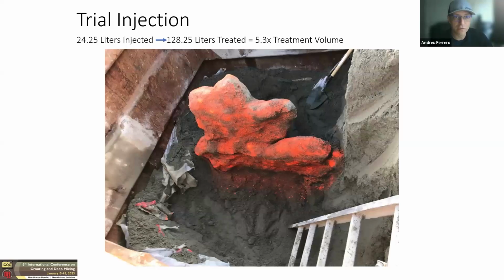This is the trial injection for the polyurethane that we injected. As you can see, it's kind of an oblong, oddly shaped structure. We injected 24.25 liters of the polyurethane, and then we measured approximately 130 liters of treated soil, which gives us about a 5.3x treatment volume. Now, if you back calculate out the soil volume from that volume, you can see that you get about a 2.5x expansion of the polyurethane within the soil, which is greatly different than the 30x expansion potential that the polyurethane has in free rise or in a cup test.